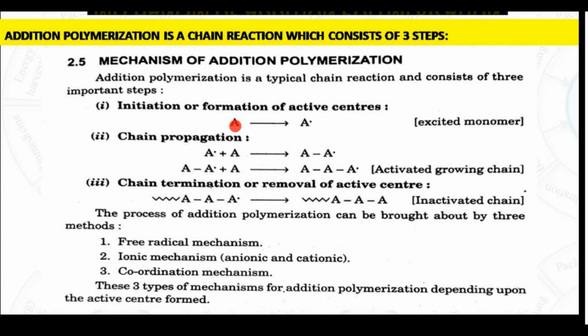Say you have this species, which is a neutral species, and it undergoes initiation in presence of certain solvents or say light or some other thing. It will produce some active species, and basically this is your initiator. This is the initiator radical. And what happens? This initiator radical then attacks your monomer, okay? And then the chain propagates. Propagation means the increase in the length of the chain to the desired value of degree of polymerization. Okay. So A, then A, and this process then gets continued.